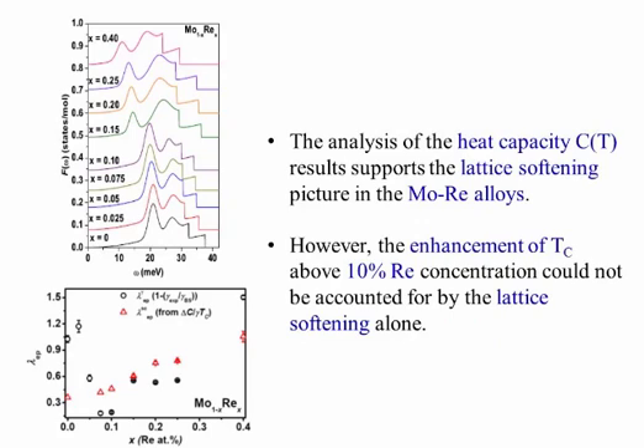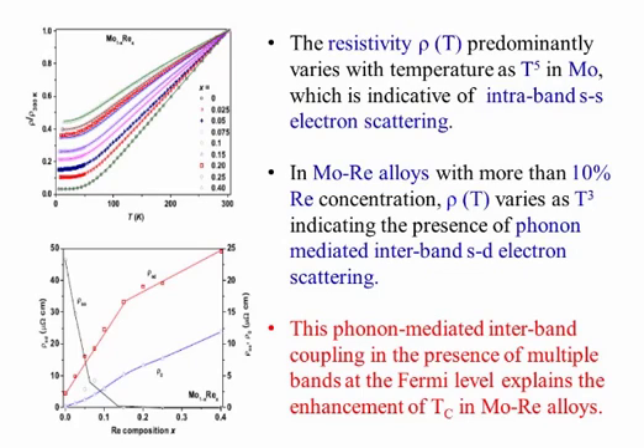The analysis of specific heat results supports the lattice softening picture in the molybdenum-rhenium alloys. However, the enhancement of TC above 10% rhenium concentration could not be accounted for by lattice softening alone. We then carefully study the temperature dependence of electrical resistivity.